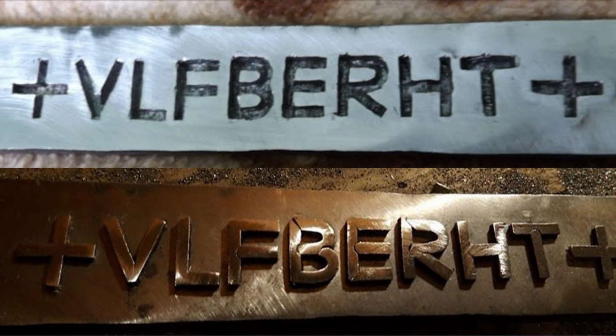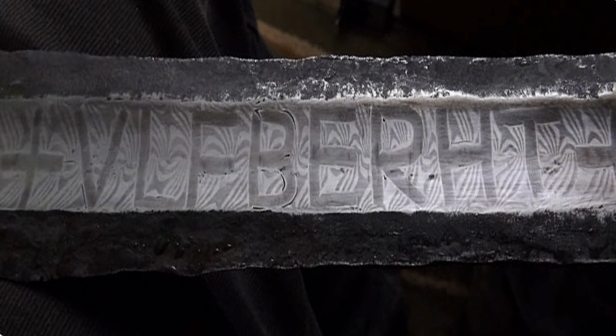This is an example by a fellow bladesmith from Poland, Rafał Garbasik. First the channels are carved, then the inlay is inserted. Finally, it is forge welded solid. You can see some of the marks left over from the process. These marks are like the ones seen in the original Vehmaa sword. Although I should point out that those defects in the inlay can also be reproduced in a different way, and I will explain that at a later time.